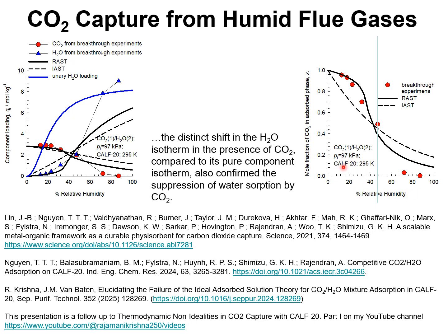At low values of relative humidity, the adsorbed phase is significantly richer in CO2, i.e. poorer in water than anticipated by the IAST. On the other hand, for high values of relative humidity, the adsorbed phase is significantly poorer in CO2, i.e. richer in water than anticipated by the IAST.